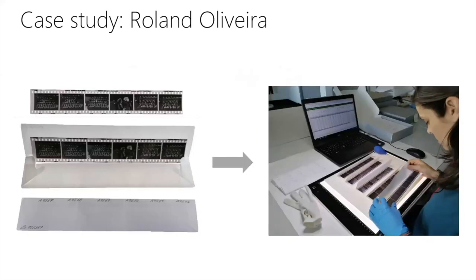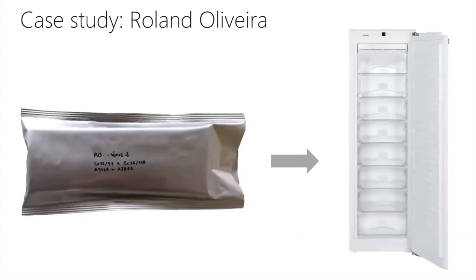After treatment, the negatives were placed inside acid-free paper envelopes. The strips can now be easily handled and digitized in high resolution with the flatbed scanner available at CDI, enabling the study and dissemination of the images from the collection. The envelopes with negatives will be sealed inside aluminium bags after the digitization process and stored in no-frost freezers to extend the lifespan of these cellulose acetate films.